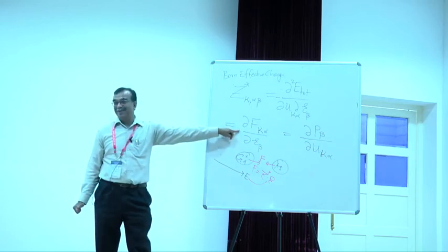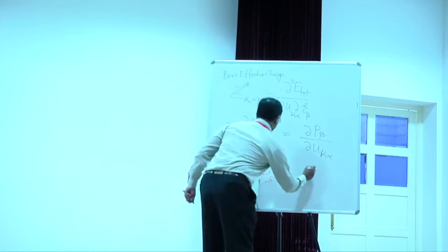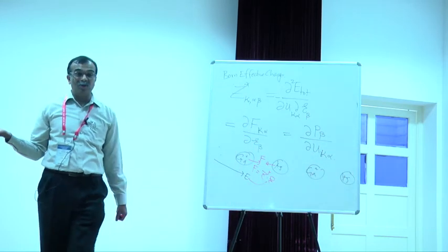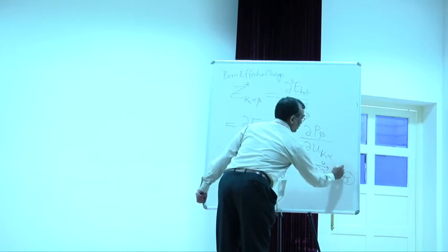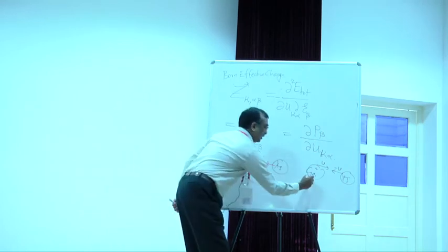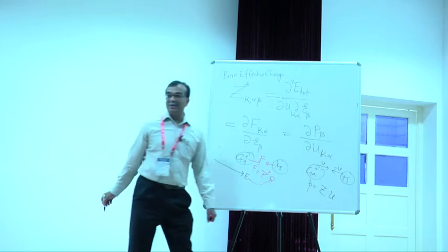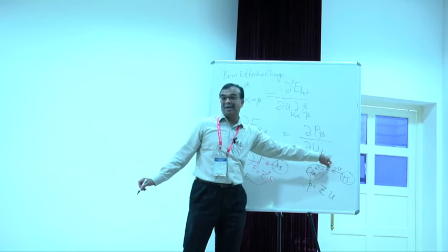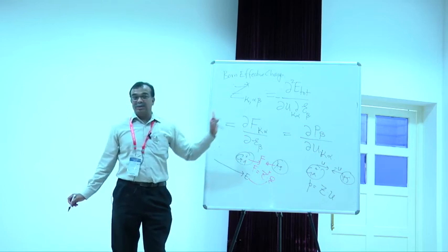That's the content of this formula, right? Linear response. What is the physical content of this formula? Suppose this is your gallium plus, arsenic minus, and you somehow excite an optical phonon in gallium arsenide, right? Optical phonon means gallium moves this way and arsenic moves this way by minus U. When the two opposite charges move in opposite directions, they will create a dipole moment, right? Dipole moment is charge times displacement. And that's the content of this formula: dipole moment induced in beta direction by the motion of atom K in alpha direction. So the Born effective charge is related to this second derivative.